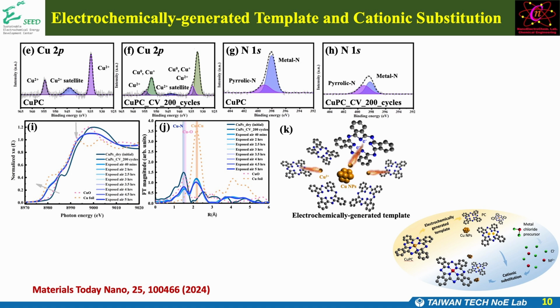For another example, in single atom catalysts, it's very difficult to produce a high loading of single atoms. We actually developed a general approach. This we call electrochemically generated template, followed by cationic substitution.